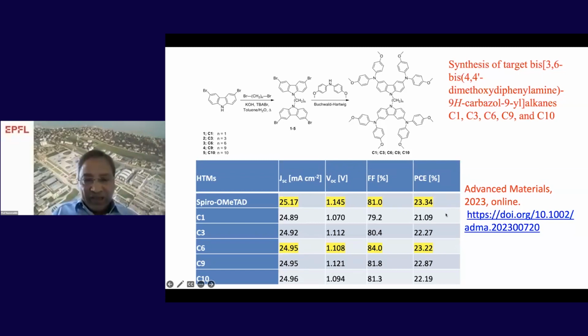So this is a very interesting flexible hole transporting material in order to stabilize the perovskite on top and to passivate the defect on the perovskite. So you can see more details on this type of HTMs in Advanced Materials, which is also online.